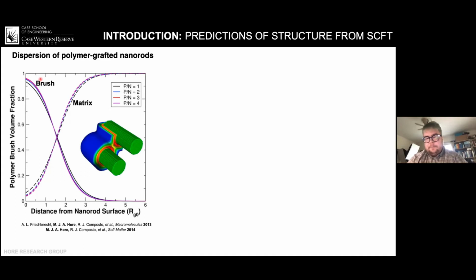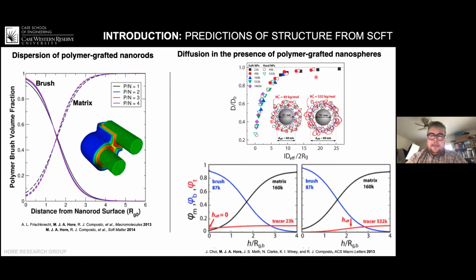But at the same time, if you look at the diffusion of polymers inside of a polymer matrix, this kind of mutual diffusion problem, you can cast the diffusion coefficients of a polymer in a nanocomposite onto this master curve. And really all it depends on here is the size of the nanoparticles. But from the same self-consistent field theory calculations, we see that this autophobic effect changes the effective size of the nanoparticles. So clearly something is going on here, and that's what motivated this project to understand these phenomena.